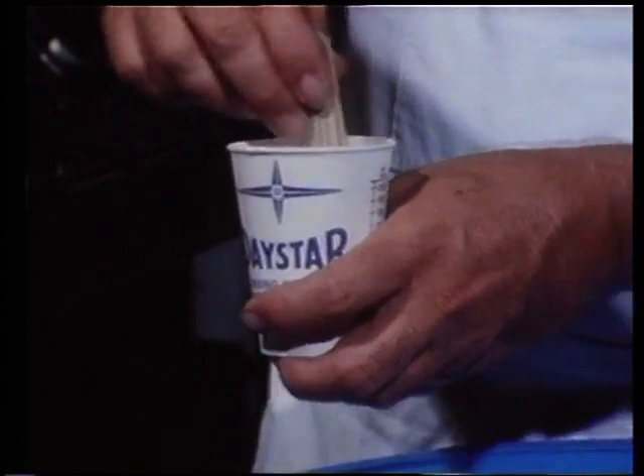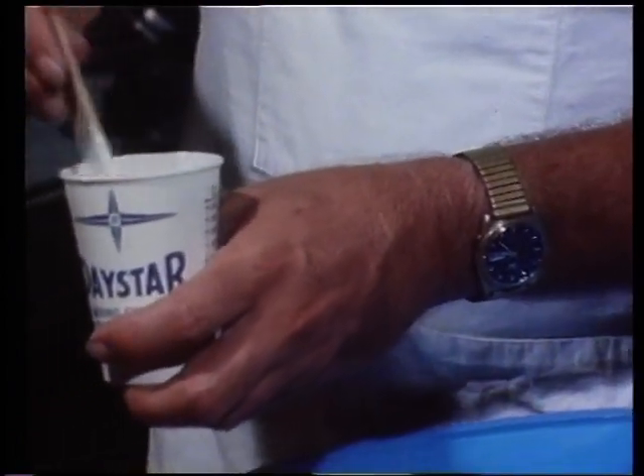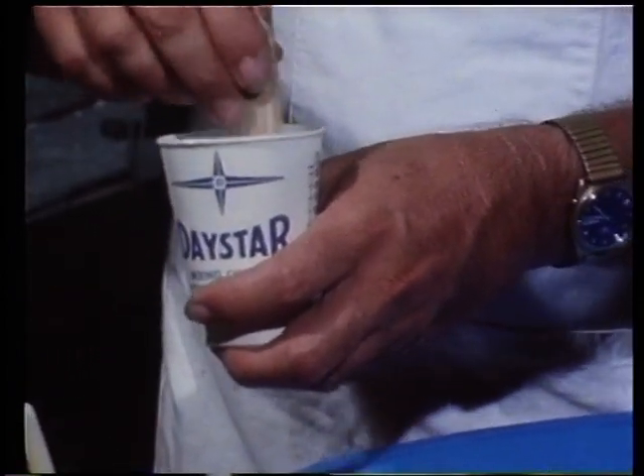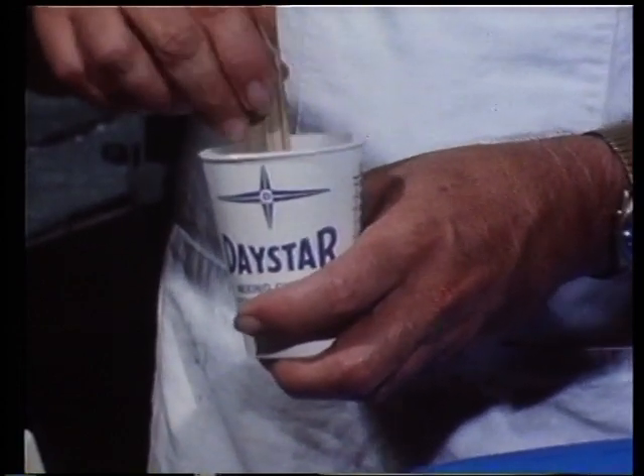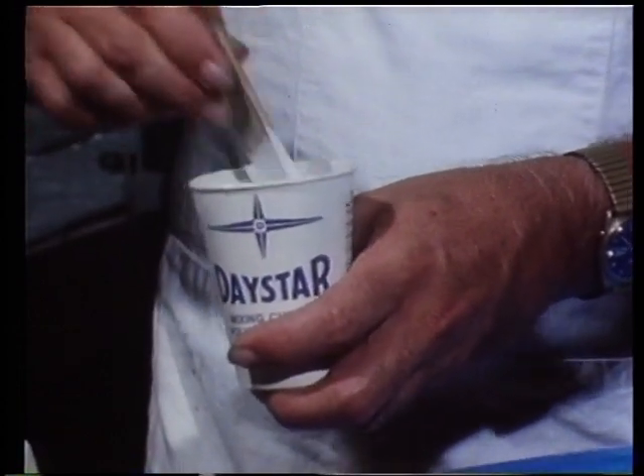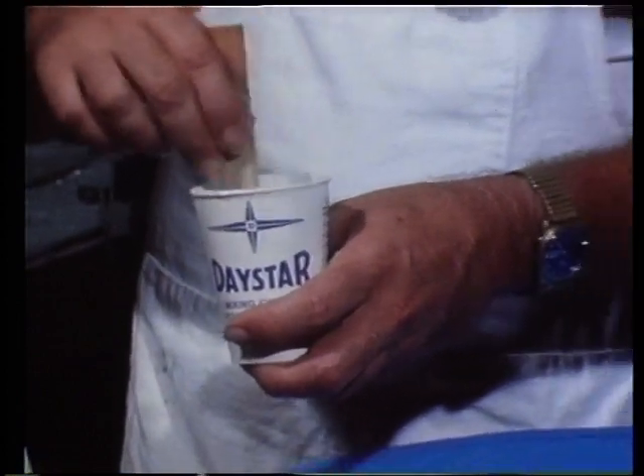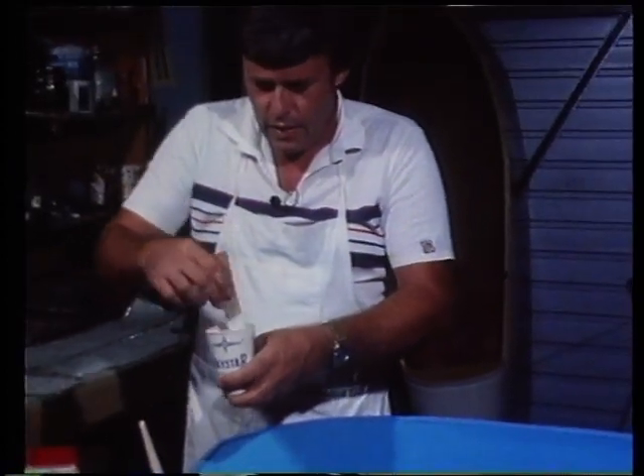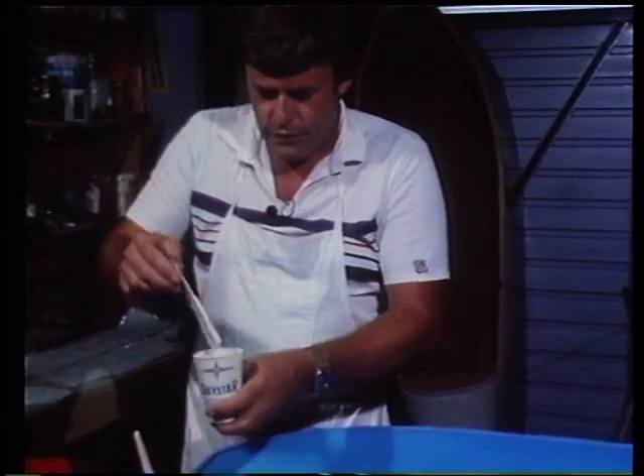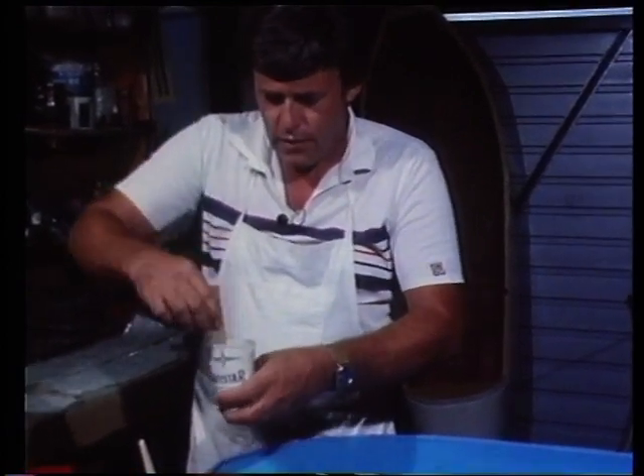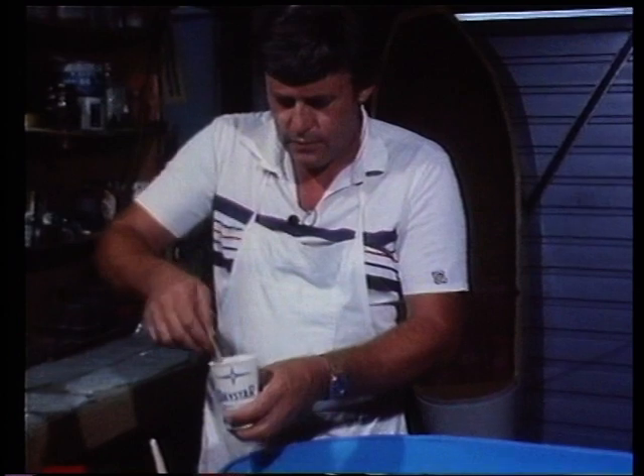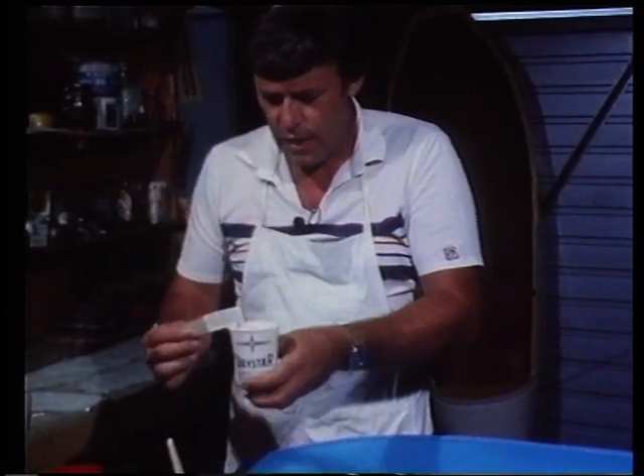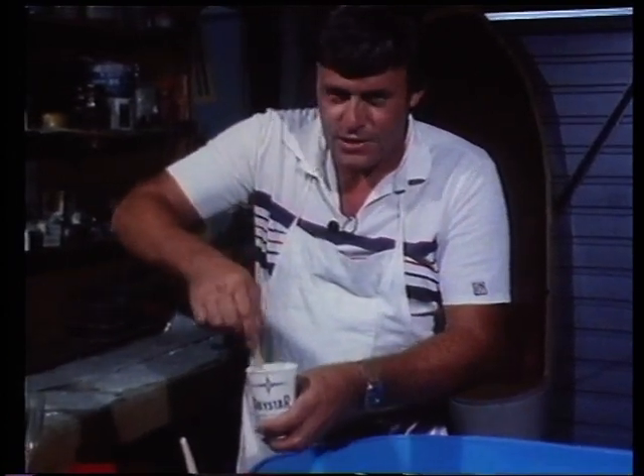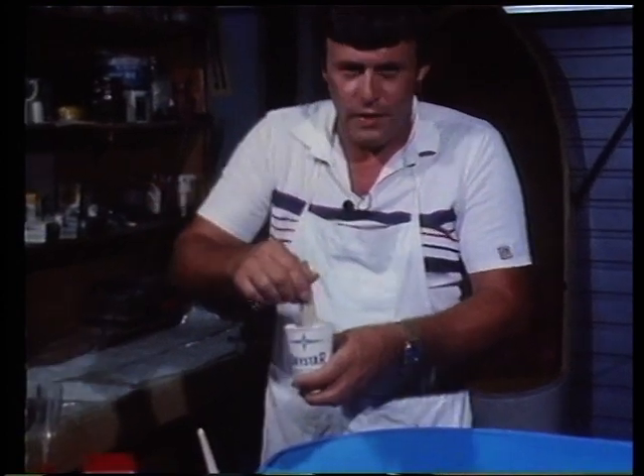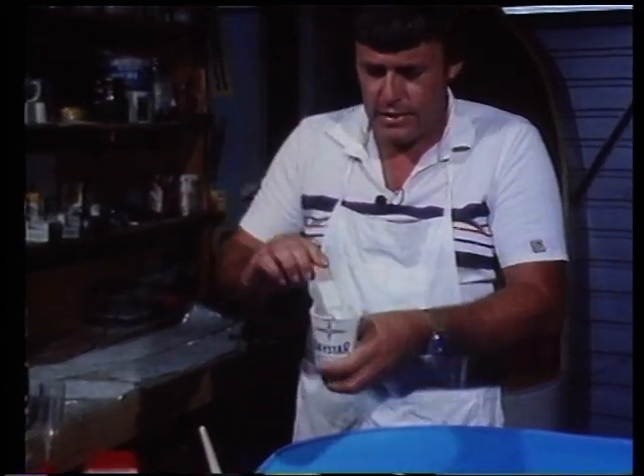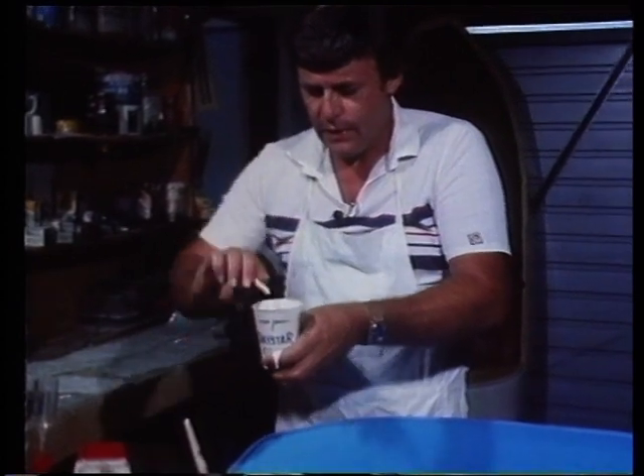I often see people in the fiberglass industry use their brush to stir the catalyst into their resin, and that is not the way to go, because the brush will have uncatalyzed resin trapped in the hairs which will not be catalyzed. So that really isn't the way to go. Now for that small container, for a fairly large stirring stick, I reckon that I've got it pretty well evenly distributed. So we can stop stirring now, scrape the stick off and stir that back into the cup, because there was uncatalyzed gel coat clinging to the stick. Just scrape it back into the cup.